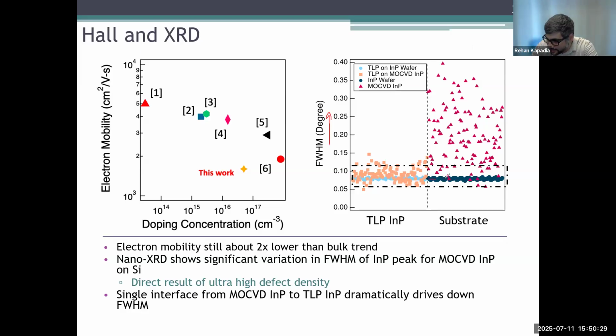And so you can see this blue line over here is what you get from just a single crystalline wafer. This light blue line is what you get from templated liquid phase indium phosphide grown on a single crystalline wafer. So you can see that basically, the quality is just as good as you would expect, because it's homoepitaxially grown on a single crystalline wafer. And then here is what you actually see from the MOCVD indium phosphide. You can see that there's a massive range of full width half maximums, and that's because there's such a large density of defects there that you get all kinds of broadening depending on which exact spot you look at. And then this is the TLP indium phosphide that's grown on top of this layer. And so you can see a very nice visual demonstration of how we've dramatically reduced that defect density here. And I think that's something that's quite interesting and unique.